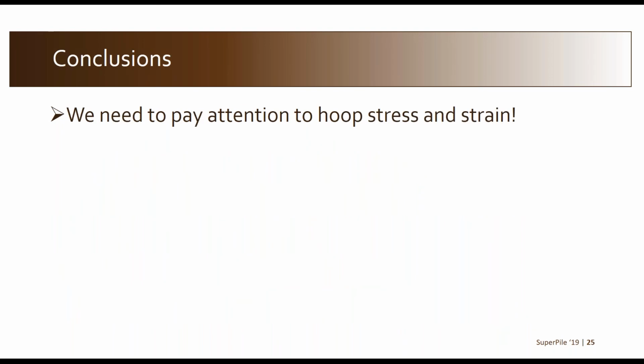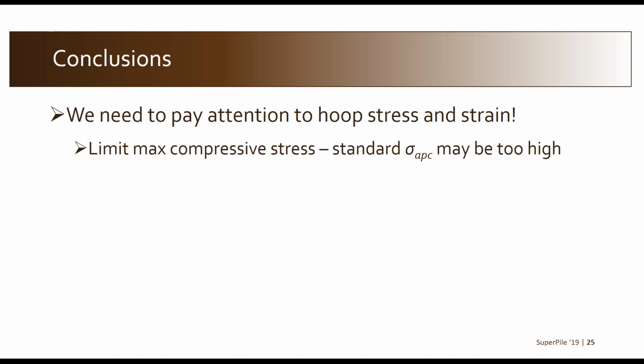So to wrap up here, the pretty obvious lesson, I think, is that we need to take a look directly at what's going on in the hoop direction in terms of stress and strain. Doing so is almost trivial in terms of the calculations, but nonetheless, that's not directly accounted for in the standard specs or in a document like AASHTO. The maximum compressive stresses that just look at avoiding crushing or tensile failure in the classic sense of driving concrete piles may be too high because it doesn't take into account this directly. So you could come up with a modified maximum allowable compressive stress during driving that makes sure you stay below the tensile strain limit of the concrete.